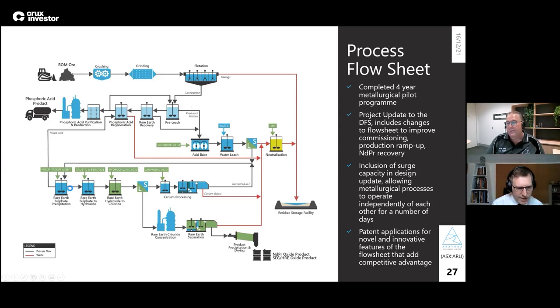Okay, and then you've got three stages, which is sulfate to hydroxide to chloride. Yes, so we basically precipitate out the rare earths as a hydroxide, purify that using magnesia and a few other minor chemicals. That's mainly to remove some of the impurities in there. We then leach the rare earth hydroxide using hydrochloric acid. We do a differential leach where we leach out all of the lanthanum, neodymium, NdPr, heavy rare earths, and we leave behind the cerium hydroxide.